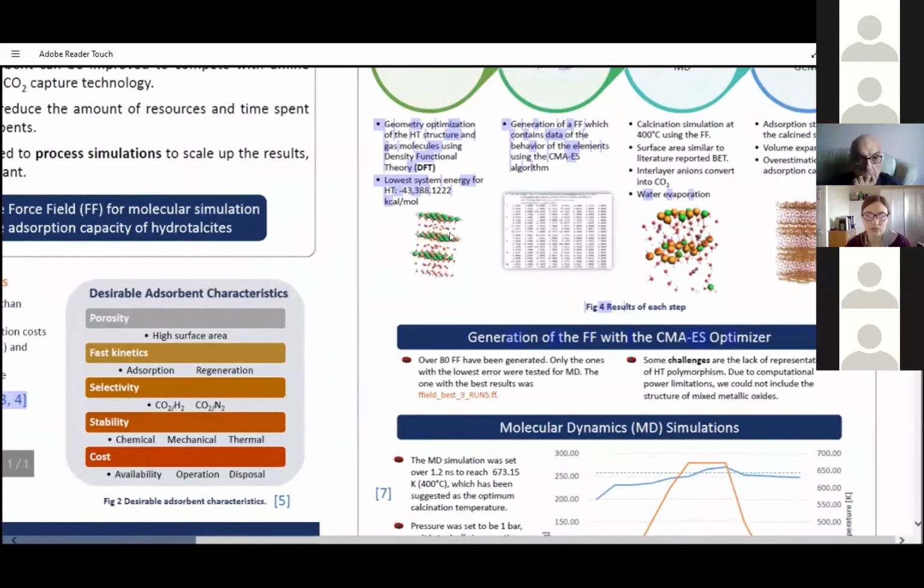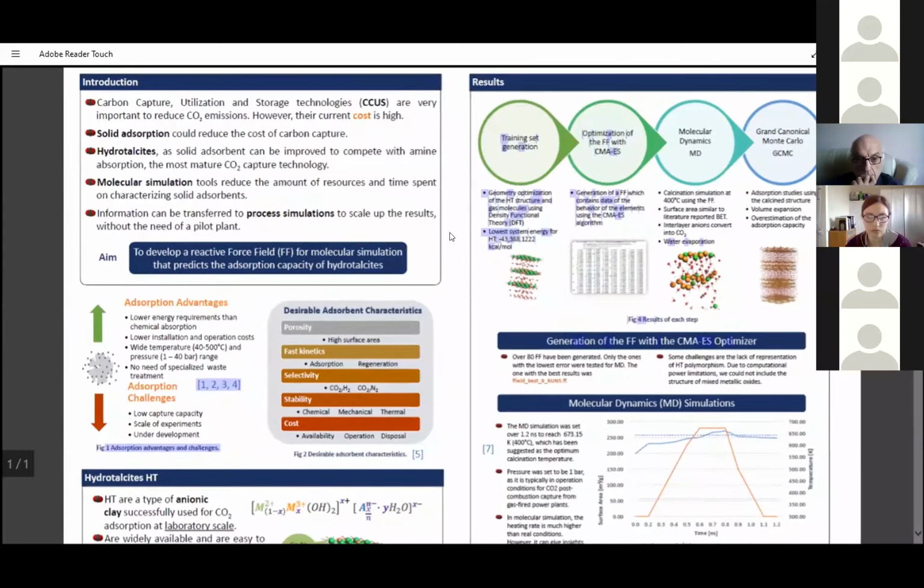When you have the material activated and it has this amorphous structure, most of the CO2 gets stuck in the part where you have the aluminum with magnesium, because there is a change in the charge around the atoms. So the CO2 is more attracted to these so-called active sites, rather than the whole structure.